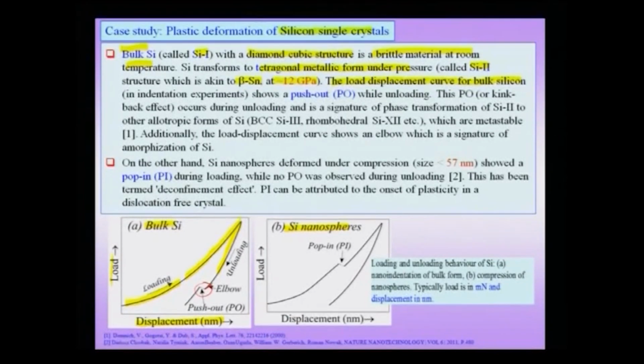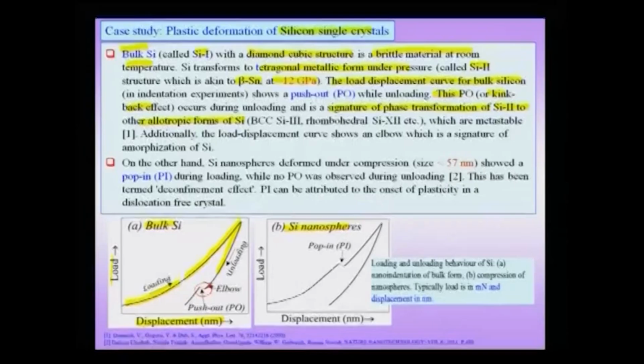Now, what is the reason for this? This PO or kink back effect, as it is sometimes called, occurs during unloading and is a signature of the phase transformation of silicon 2 to other allotropic forms of silicon. So, you have silicon 1 which transforms to silicon 2 under high pressures under the indenter, but when you unload, that means now you are relaxing the structure, this silicon 2 transforms to other allotropic forms like silicon 3, which is BCC, or rhombohedral silicon 12 structure, which are metastable forms of silicon. Additionally, this elbow part which I mentioned is a signature of the amorphization of silicon. So, some part of the silicon is also getting amorphized.